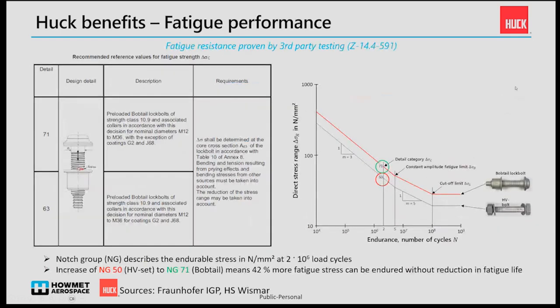The special design of the Lockbolt in regard to the lock grooves also results in a very high fatigue resistance. So when you have a look at the conventional thread, as we have seen on the previous slide, we see that there's a very sharp notch in the thread area. And this leads to some stress concentration, resulting in a very low fatigue resistance of a threaded fastener.